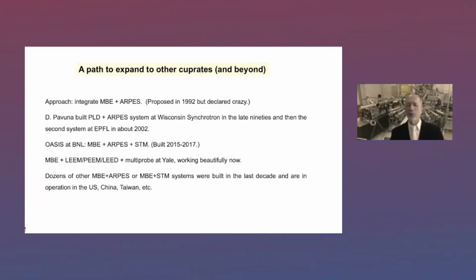Well, one path, which may not be the simplest, would be to integrate MBE and ARPES or MBE and STM. And then you grow by MBE, and under UHV transfer it to ARPES or STM. I proposed this in '92, but it was declared crazy. Actually, as recent as 2010, our proposals from BNL to build the MBE plus ARPES plus STM system were turned down because referees said it's impossible, it cannot be done.